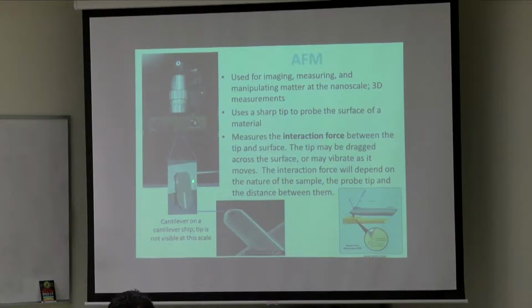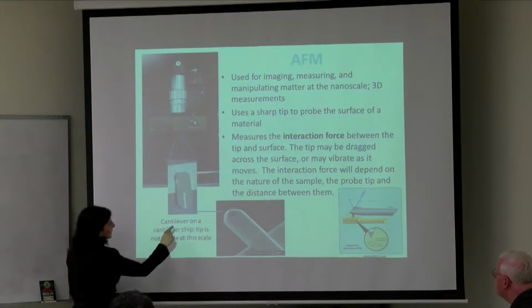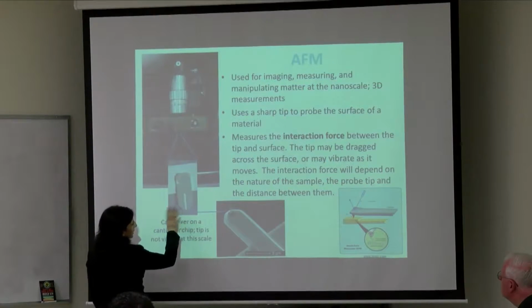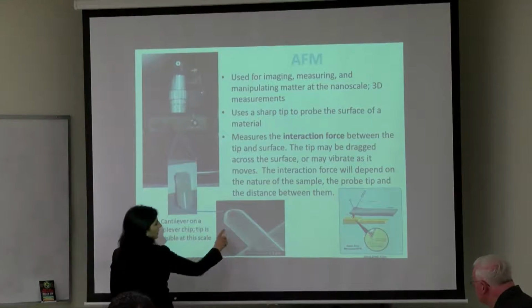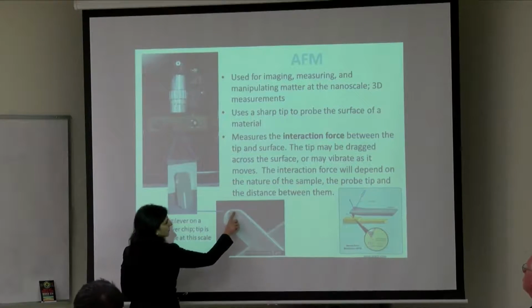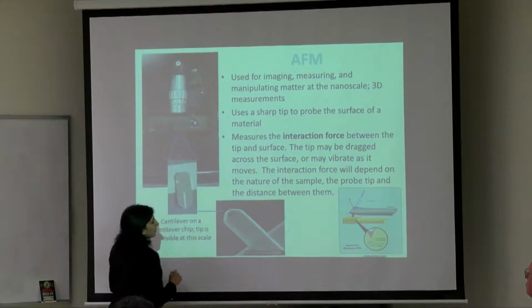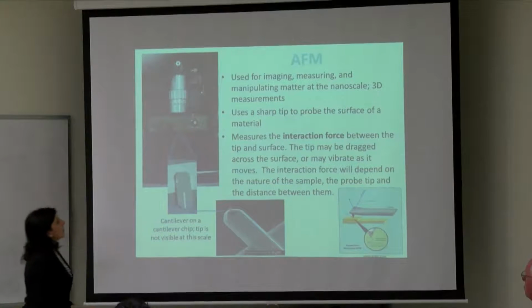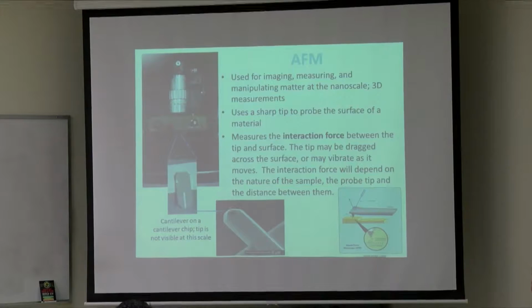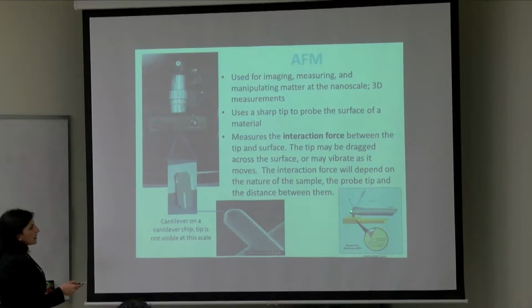This is the cantilever chip, and this line is the cantilever. You really can't see it because the resolution is bad here, but it looks better on the slides. Down here, which you cannot see at all, is the actual tip. If you see an SEM picture of that, here's the cantilever, which is this white thing here, and at the very end of it, there's this sharp tip. The scale of this is 5 micrometers. The atomic force microscope is used for imaging, measuring, and manipulating matter at the nanoscale. So you can take 3D images of your sample. This sharp tip is what's used to probe the surface, and it does that using the idea that there are interaction forces between this tip and the surface of your material. This is the cantilever here, which is this arm, and the little tip. And the tip goes across the surface.